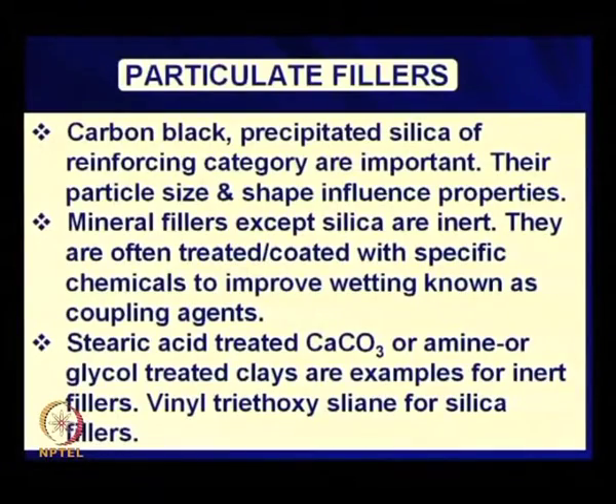Can you tell me the source of fatty acid? Source of fatty acid? Vegetable oil. Vegetable oils are glyceride esters of fatty acids, triglycerides of fatty acids. So, that fatty acid can be taken from or extracted from oil, and that fatty acid can be dissolved in a solvent, a dilute solution, then make a spray coating on these filler particles. What will happen? The solvent will evaporate out and there will be a thin coating of stearic acid or this fatty acid on the filler particle. So, it will be an organically modified filler, and that can easily be blended with polymer.